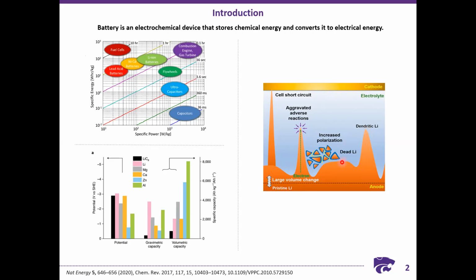Another thing that can happen is the formation of dead lithium. After we plate the lithium metal, when we strip in the following cycle, the Coulombic efficiency is mostly low, so it's not 100%, so there will be still some lithium left, and the formation of SEI over the lithium results in dead lithium, which cannot be utilized in the further cycles. As the cycles go on, the accumulation of this dead lithium results in also the accumulation of new SEI, resulting in an increase in the resistance for the cell, resulting in failure of the battery.